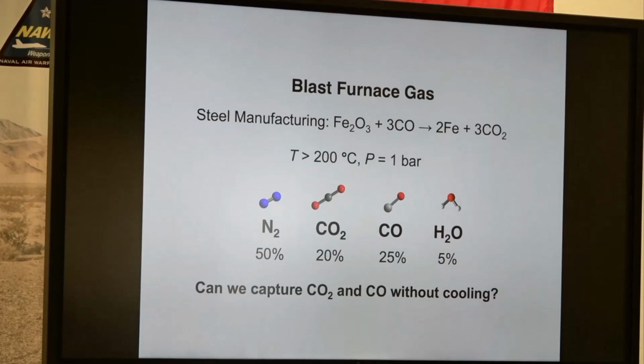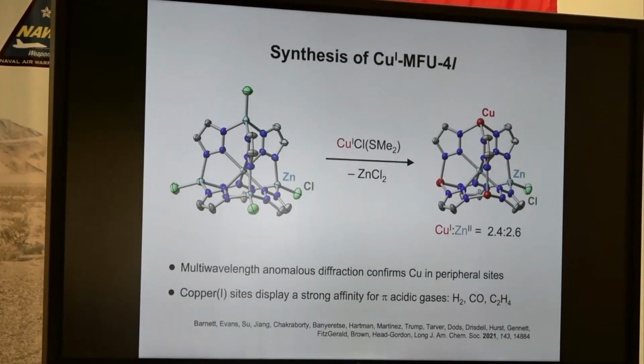Okay, briefly, let's come to carbon monoxide. We also have high temperature carbon monoxide we'd like to capture. And to do that, we want to get to something that's really a very good pi donor. So one thing CO can do is make really strong pi bonds with the metal. And a great metal for doing that is copper-1. Copper-1 has two orbitals to make pi interactions with CO that are filled. And so this should work, copper-1 sites, if we can replace the zinc chloride with copper-1, which we can by this reaction, you create a pyramidal copper-1 site with an open face for coordinating CO.